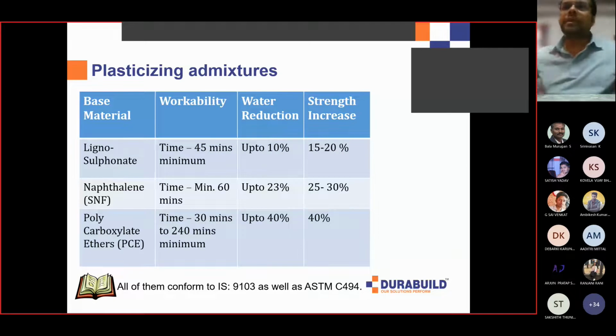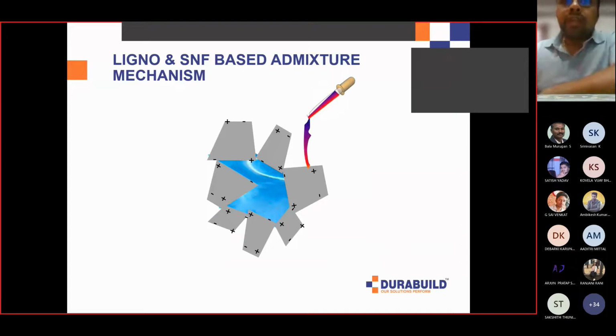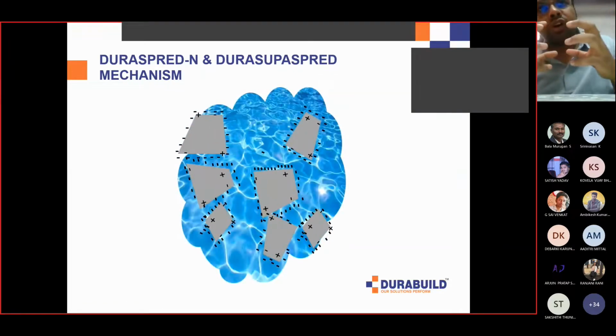What is happening is, the moment you are mixing cement, water, sand and aggregate, the cement has a tendency to agglomerate. You must have seen that, to come closer to each other. It is because of the surface charges which are there in the cement particles. So when you are adding these chemicals, and this slide mentions it, if it's a ligno and SNF based admixture, it creates a negative zeta potential, or creates a negative charge around cement particles. And I think many of you already know, like charges repel each other. So the moment you have negative charges, automatically the cement particles go away, and the water which is locked inside gets released, and that's how you get the flow in the concrete.